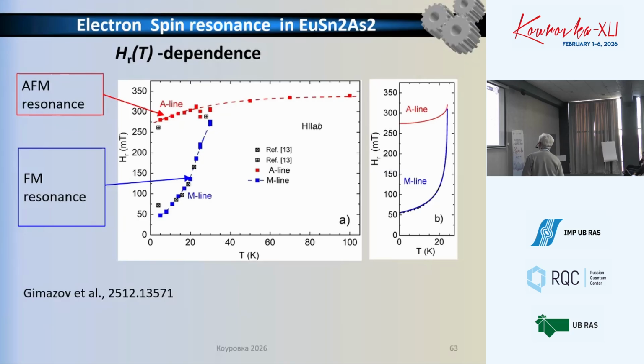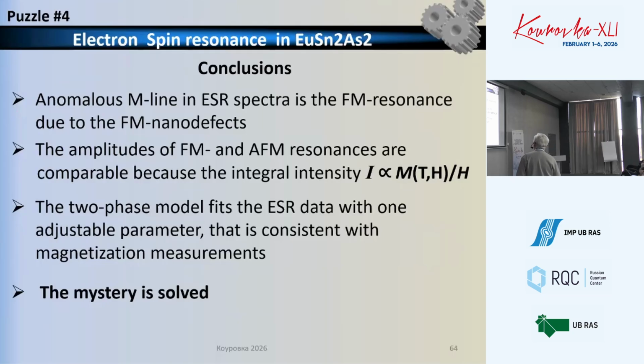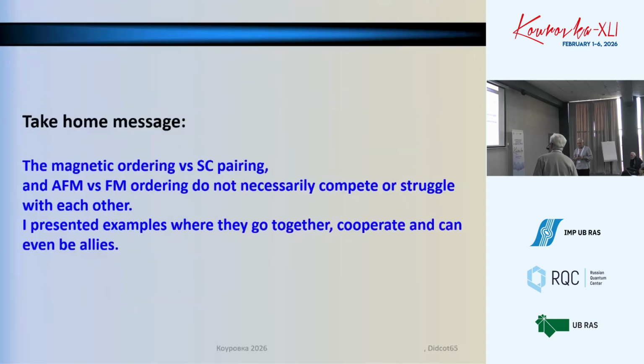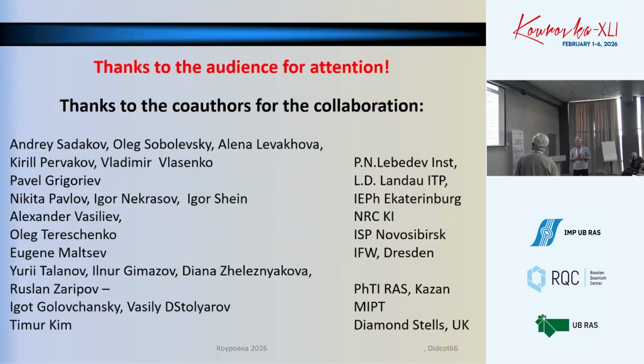So I believe that we understood that the ferromagnetic resonance indeed develops due to the planar defects. The amplitude of the ferromagnetic resonance from this tiny planar defect is comparable to the amplitude of the antiferromagnetic resonance, because the integral intensity is quite comparable. So I believe that the mystery is solved, and I suggest for young attendants the take-home message: the magnetic ordering versus superconducting pairing, and also the antiferromagnetic and ferromagnetic ordering, do not necessarily compete or struggle with each other. They may go along, and I present examples when they cooperate and can even be allies, but I don't have time to speak more about it.